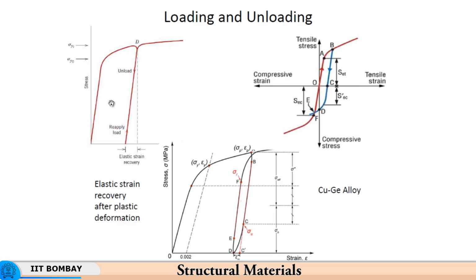The area of this loop signifies the energy dissipated inside the material. While loading and unloading, you have a different path. Here the path was the same, so the area in this loop was exactly 0 in that case, but here the area is not 0, and therefore it is proportional to the energy dissipated during this loading and unloading cycle. This will result in an increase in the temperature of the alloy as it undergoes loading and unloading, because this dissipated energy will appear as heat.